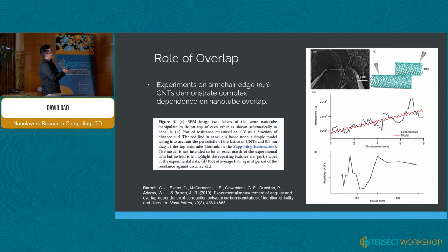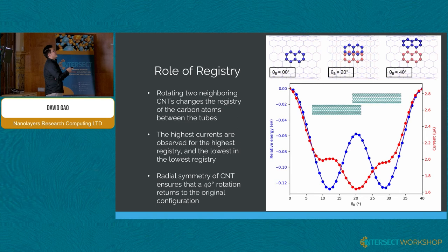And it turns out that you can think about this using the concept of atomic registry, which basically sums up how well the patterns on the nanotubes coincide with each other. So in these images, there are two sets of hexagons, a red one and a blue one. In the first panel here, they're on top of each other, so you can only see the blue one. And in the second one, you can see how the blue one is offset a bit from the red one. So you can imagine the nanotube containing the blue ones is out of the screen towards you in the audience, and it's basically rotated up by 20 degrees. And by symmetry, once you get to 40 degrees, you end up with the exact same structure as you had